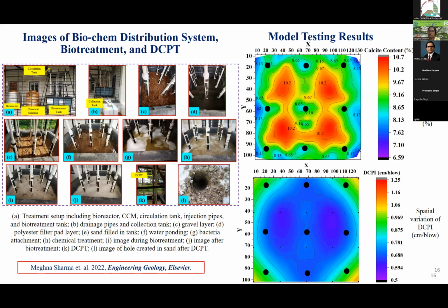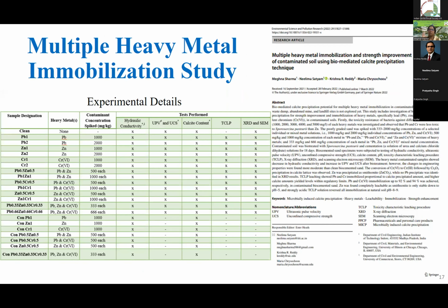Then the dynamic cone penetration index was determined, as the depth of penetration of the cone per number of blows. At the center zone, the DCPI value was found lesser. A lesser DCPI value means higher denseness of the soil, and the higher denseness is because of higher calcite precipitation. Through IS 1893 code analysis, we also determined that this biocemented or biotreated sand was found non-liquefied. So the aim of liquefaction mitigation was achieved in this study. I have just elaborated the hazard mitigation.